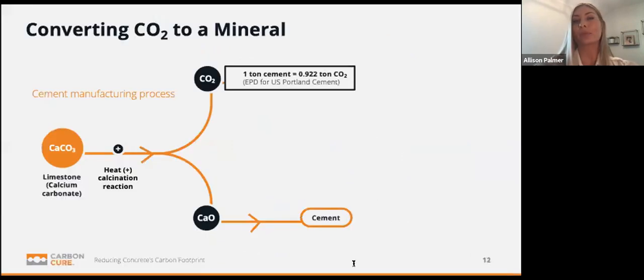So to understand our process of CO2 mineralization, I just need to do a 500-foot view of how cement is made. So cement starts by mining limestone, aka calcium carbonate from a quarry. We heat that up to about 2,600 degrees Fahrenheit, and that molecule actually splits in half. Half becomes CO2, which is the waste byproduct. And as you can see, 1 ton of cement produced equals almost 1 ton of CO2 emitted. So a huge environmental impact here in the cement manufacturing process. The other half of that molecule becomes calcium oxide. This is the critical binding material needed to make cement.